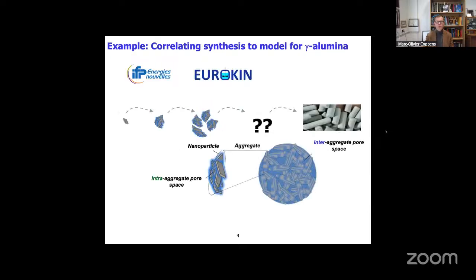So the first example, which I will get back to also at the end of my talk, is about correlating synthesis to a model for, say, a very common porous material used in industry for adsorption, catalysis, as a catalyst support, which is gamma alumina. And this is something, for example, that IFP Énergies nouvelles in France have been studying, and we've had some projects together, also in the context of the Eurokin network. So in these materials, they are hierarchical materials. You have alumina platelets, you have aggregates formed out of nanoparticles, and you have an intra-aggregate pore space. And then between these aggregates, you also have a pore space.